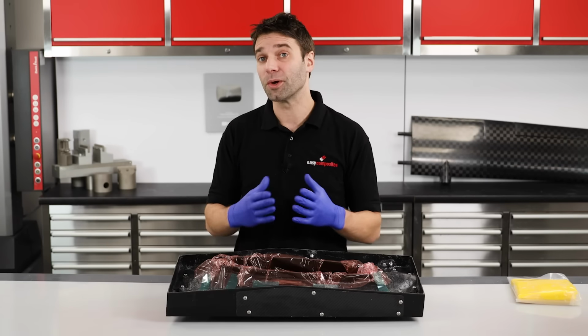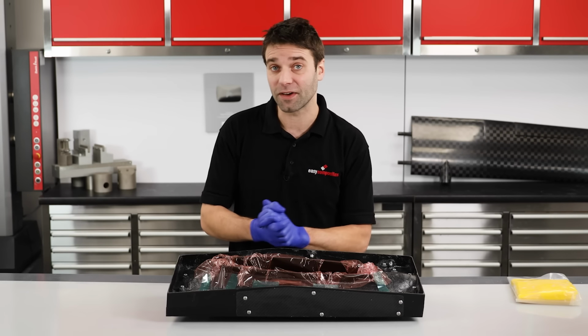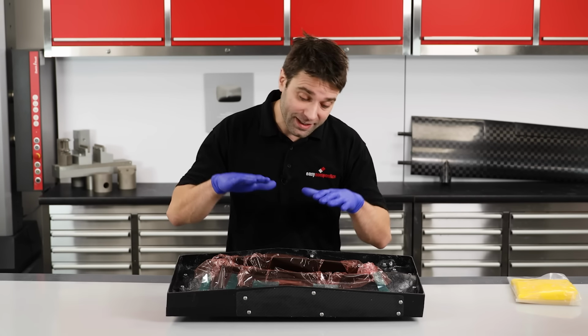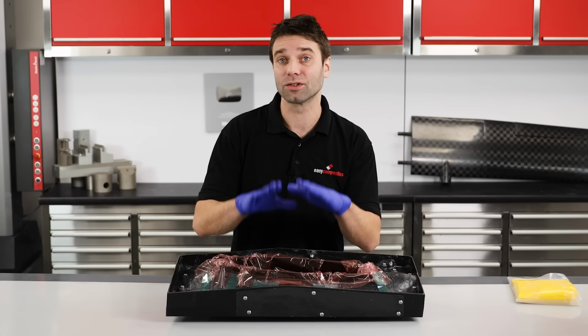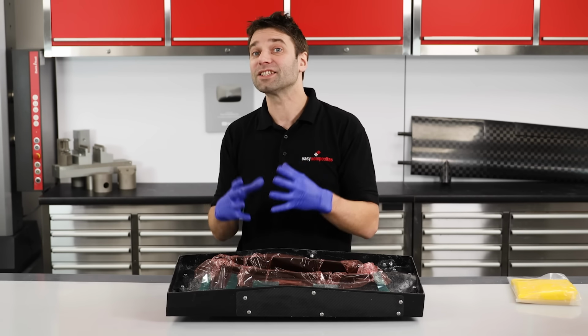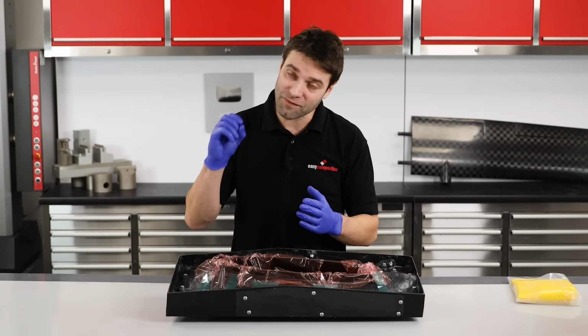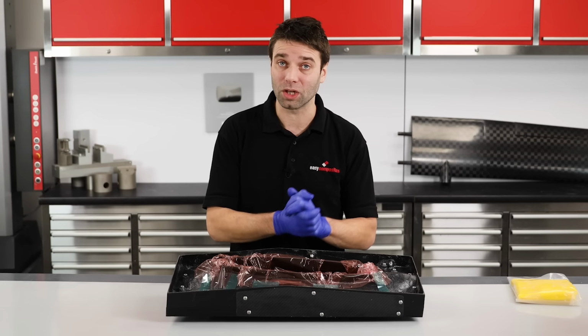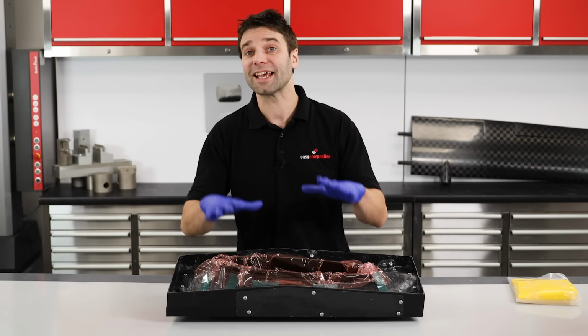With the release film down, I'm now going to take the opportunity to show you how you would normally use this intensifier material. Earlier, we made the intensifiers directly against the tool surface. Now this is only possible to do if you're going to have a very thin laminate of 1 mm or less. Normally, you would do it at this stage.